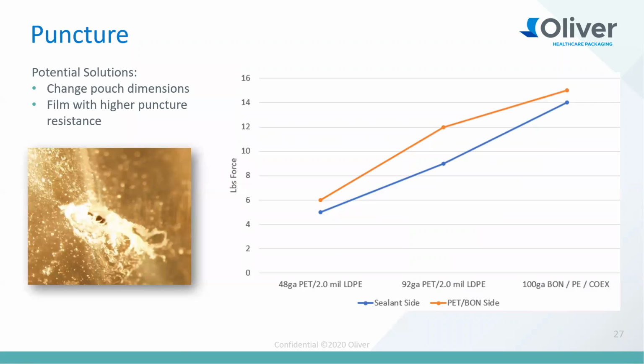This is a really good slide, and it gives a really good description of what Jeremy mentioned earlier when he was talking about flex crack, that thicker is not always better, but that's for that situation. Now, if we look at puncture, we have a nice graph which illustrates a 48 gauge polyester PE. Then we have the graph showing the puncture resistance for a 92 gauge polyester PE, and then finally 100 gauge biaxially orientated nylon. The graphs show both the sealing side and the outside of the material. And you can see it's very clear that with a 48 gauge polyester, your puncture resistance is anywhere between 4 to 6 pounds of force, whereas if you look at the 100 gauge nylon, the puncture resistance is significantly higher.